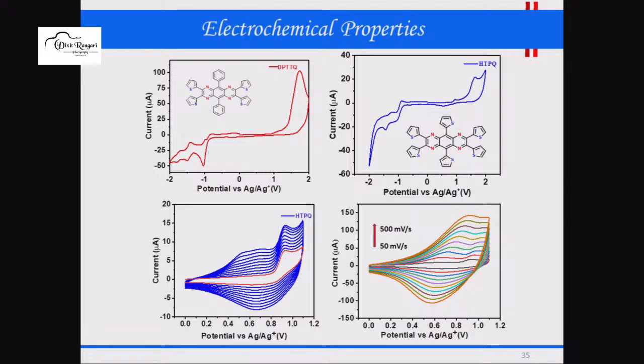So we were confused that there is also thiophene in this molecule. Then what we thought, you can see, when we do the polymerization, each cycle of cyclic voltammetry, you will get more anodic as well as cathodic current. And this anodic and cathodic current will be linearly spaced. That linearity basically tells us that our resulting polymer is an electroactive polymer. Seeing this graph, we can tell whether this molecule is electroactive or not, and it also tells whether it is undergoing a polymerization process or not.